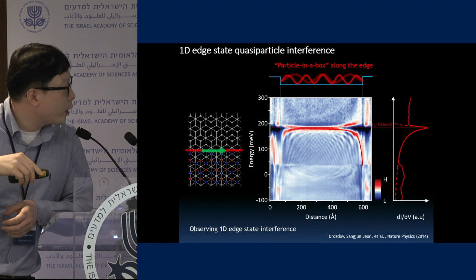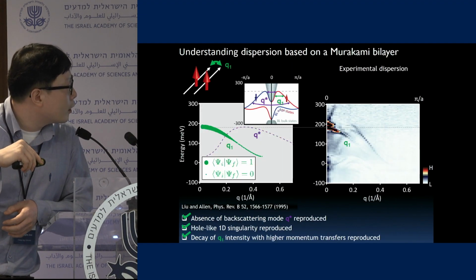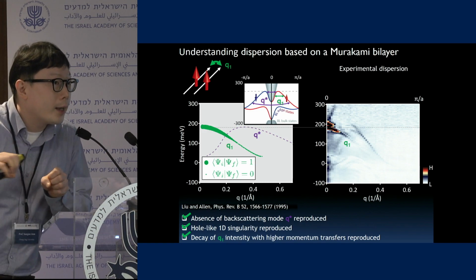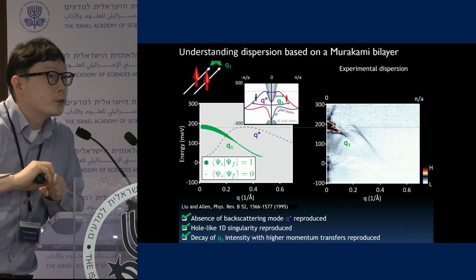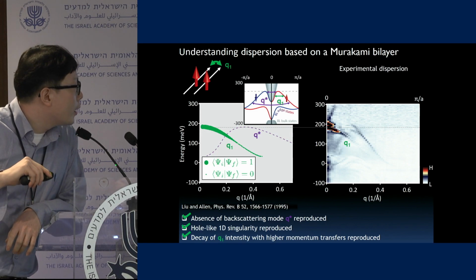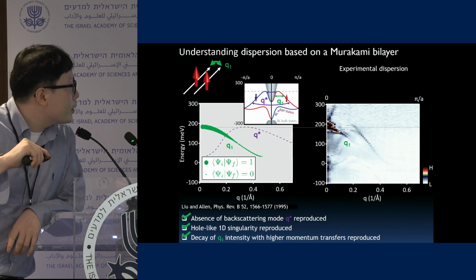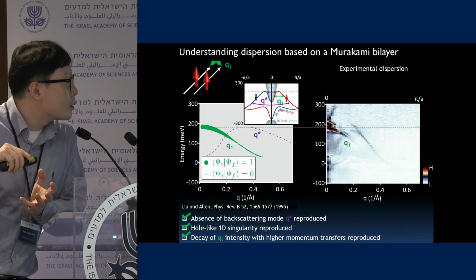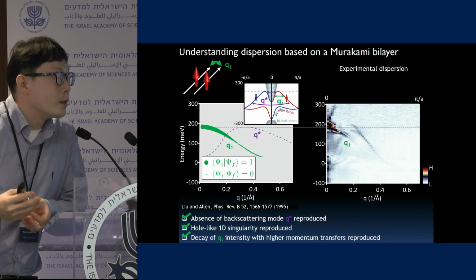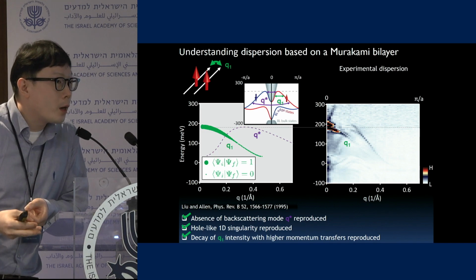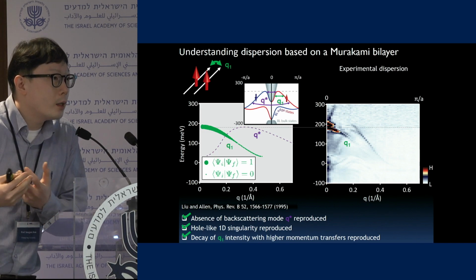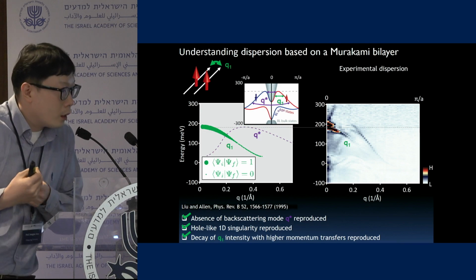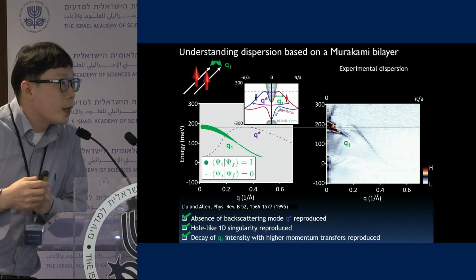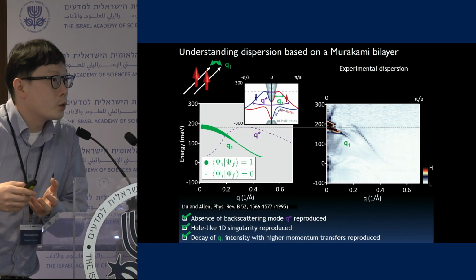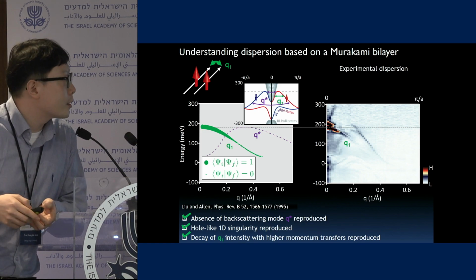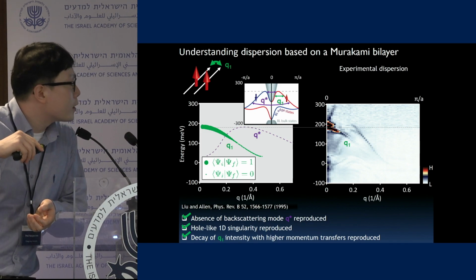And by Fourier transforming it, we can understand the dispersion of electron states lying localized at the end of the step edges. Then by analyzing the data, we found that there is no backscattering in there. That means there should be a spin up component and spin down component, but they are living in different states, so they do not interact with each other. In other words, this could be a signature of helical edge states living in one-dimensional states.